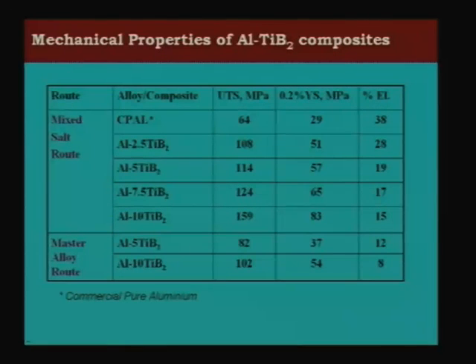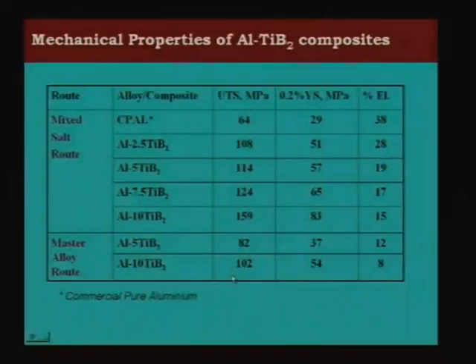At those high temperatures, there is always a possibility of gas absorption. Aluminum strongly absorbs hydrogen. So that is another problem one has to control. So how to control gas absorption by this aluminum? High temperatures lead to that, and because of which the elongation comes down and the strength also comes down to some extent. So that's why the mixed salt route is commercially also more viable, because you are not really going through a 3-step process of making 2 master alloys first and then remelting them together, and also at the same time one can achieve much better strengthening.